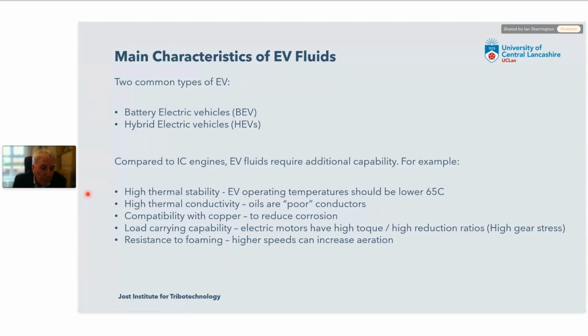We need to have high thermal conductivity to take the heat away from the mechanical elements that we want to cool. As one of Ali's slides ably demonstrated, there's a challenge here because the thermal conductivity and the specific heat capacity are in direct opposition. So as we increase the conductivity, the thermal capacity tends to go down. We need compatibility with copper, and we need fluids that have high load carrying capability. So the greatest torque appears at the lowest speeds with the highest loads, and we need to manage the high stresses that places on lubricants. And there are lots of other requirements as well, resistance to foaming and so forth.